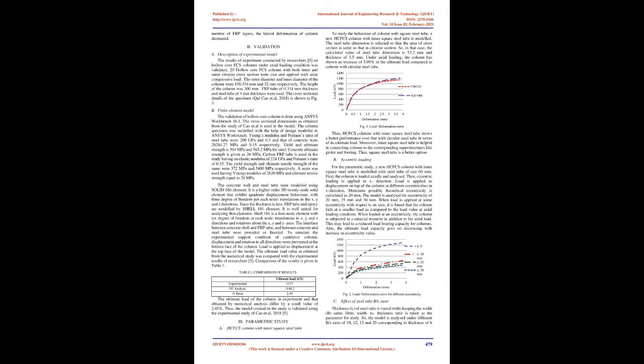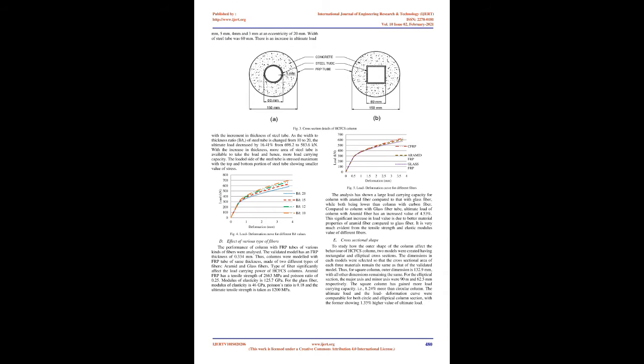So, in that case, the calculated value of steel tube dimension is 53.2 mm and thickness of 3.5 mm. Under axial loading, the column has shown an increase of 5.09% in the ultimate load compared to column with circular steel tube. Specimen was modeled with the help of design modeler in Ansys Workbench.